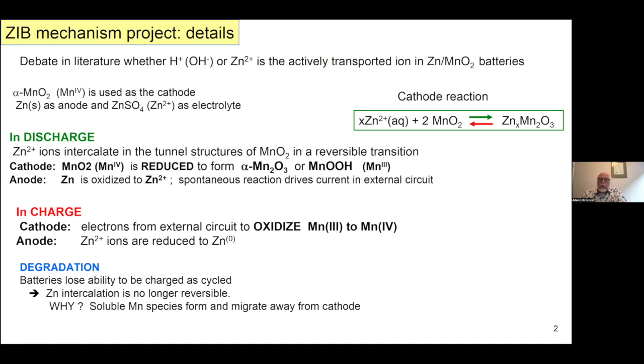And again, within our picture of what this battery is doing, the reason that's happening is that it is not a simple manganese 4 to manganese 3 oxidation state change, but you get disproportionation of the manganese 3 to some manganese 2, which is no longer a reversible component of the redox chemistry that's going on. So those are the things we were looking for based on our understanding of the operation of the battery.